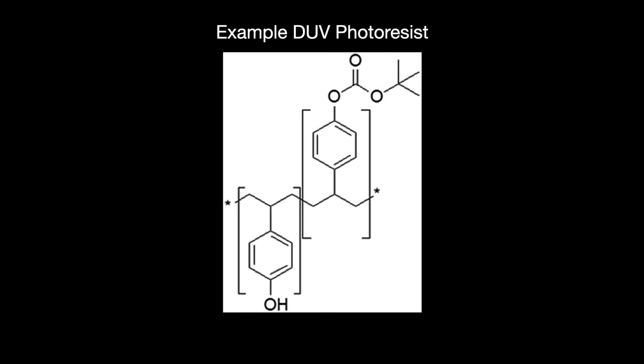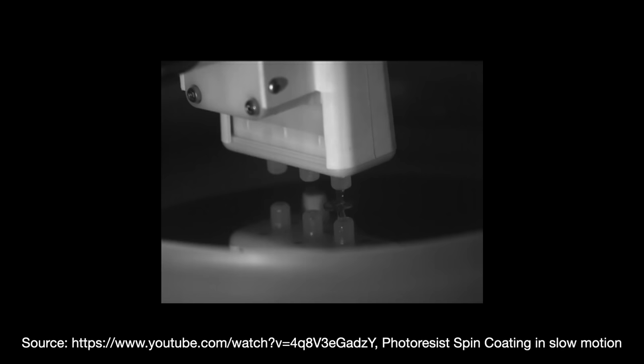In order to make sure that the wafer can receive that pattern, we apply a photosensitive chemical called a resist on top of it. The resist is kind of like film: it gets exposed to light and chemically reacts to that light, leaving behind an imprint of a chip pattern. To apply the photoresist to the wafer, you first spin the wafer at about 3,000 revolutions per minute — like the world's most expensive pizza dough. Then we pour the photoresist on top of it at its center, and the resist will evenly spread out over the whole wafer.